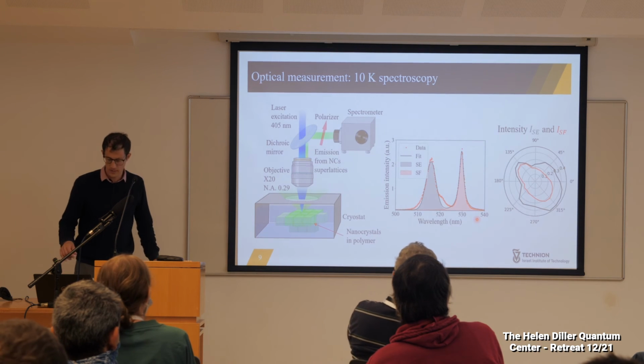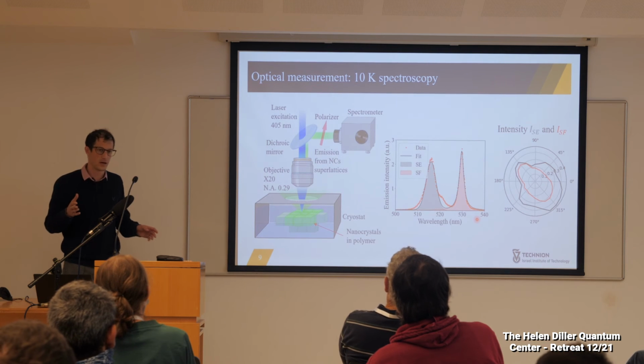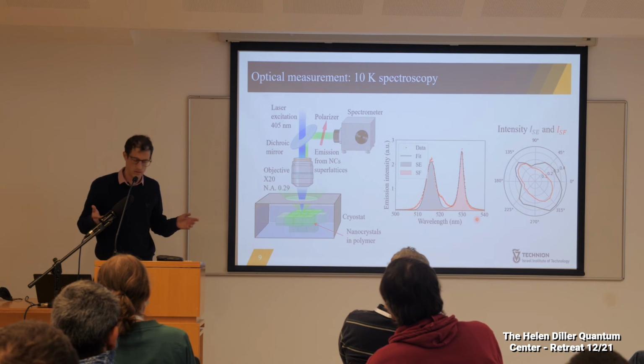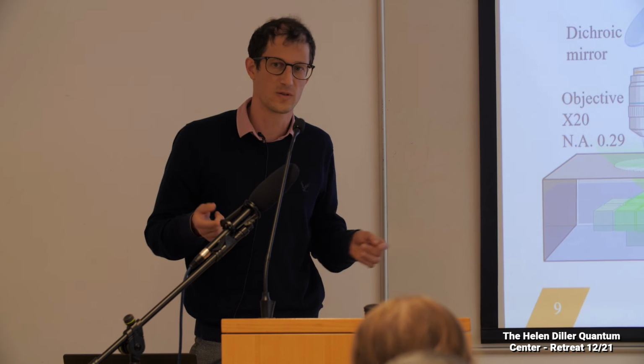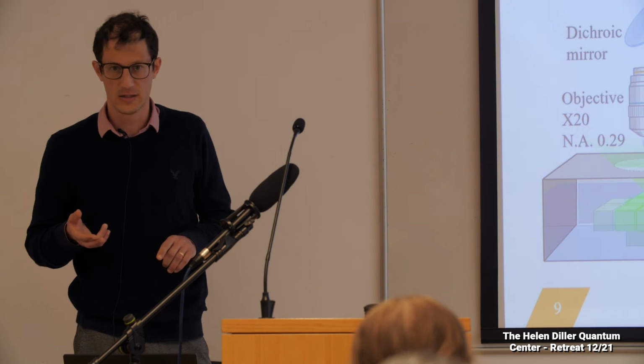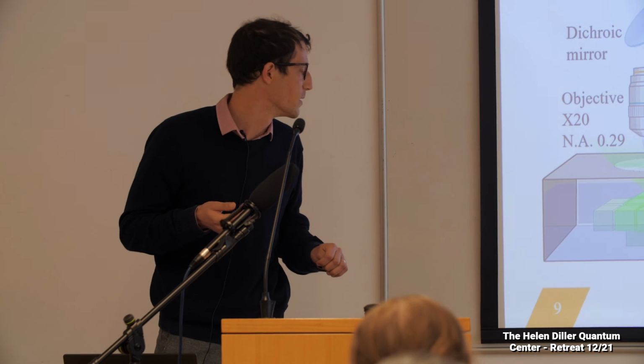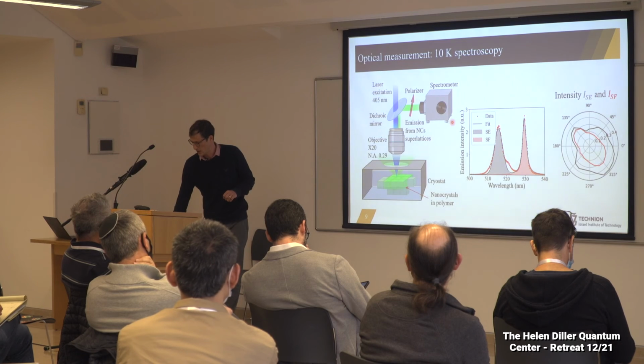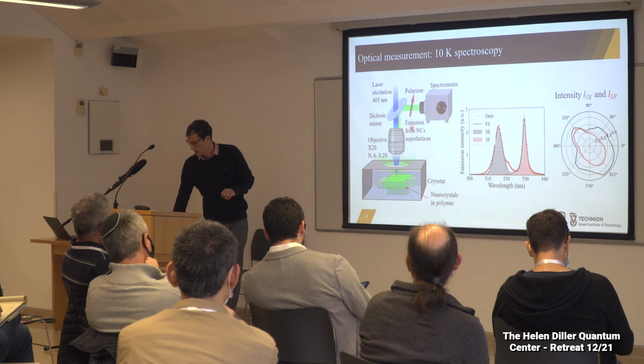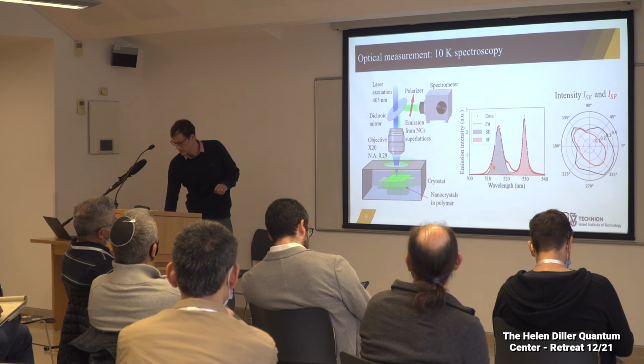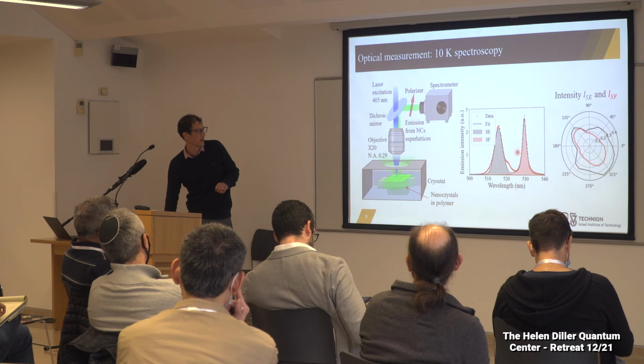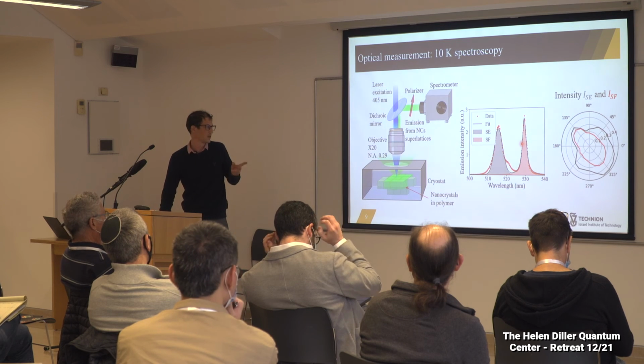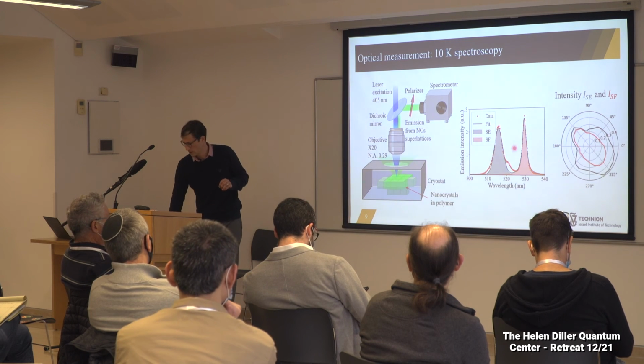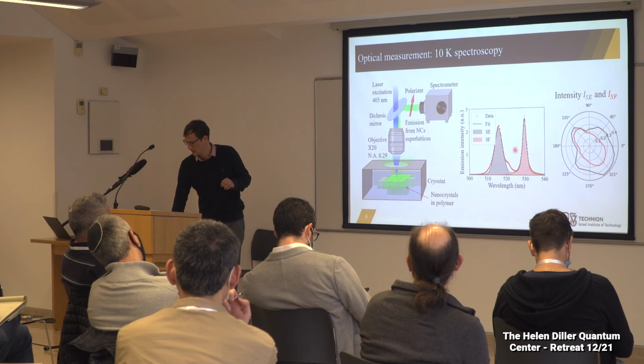This experiment took place during COVID time, and the tool was in some limited availability. We used the tool once in Switzerland and once in Paris. So we had to do some complementary optical measurements at the Technion, and we did this. We measured the spectrum at a temperature of 10 Kelvin, and we see more or less the same features. The interesting thing here is that we see both the superfluorescence and the spontaneous emission at the same time, unlike with the electron, where we need two different experiment realizations to see each peak. So here, in the optical regime, we see them together.